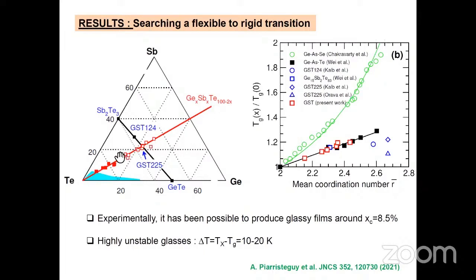Only a select number were exhibiting a glass transition temperature, that's the filled boxes. But clearly we can see that we can form amorphous systems. We also extend now the glass forming range of this ternary, which is the blue zone, which is known to have a very, very small glass forming range. We extend it now to this particular join.